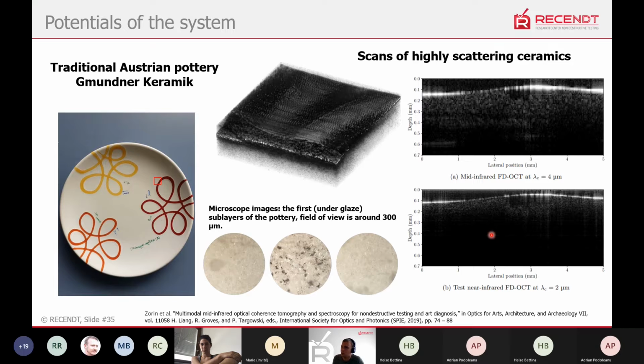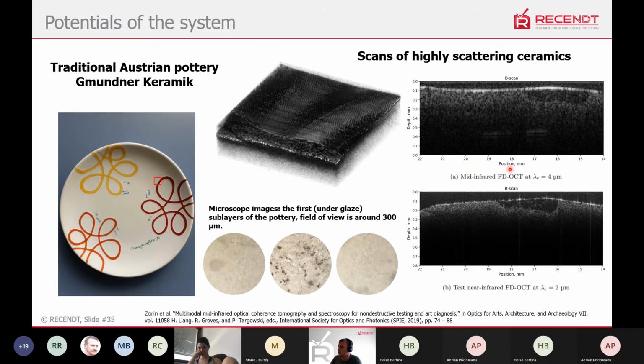I worked a little bit on investigation of different ceramics and art objects, and here it can be quite of interest. For example, this is just traditional Austrian pottery, and we could see in, and this a little bit like the black line, which is less scattering, so there are not so strong speckles here. It's due to some production layer that they heat, make some thermal treatment of the sample, and then apply the next layer. So it's not an artifact but something real, and it can be then used for some quality control. Yeah, it was very quick tests. The same could be more or less seen in this 2 micrometer OCT.